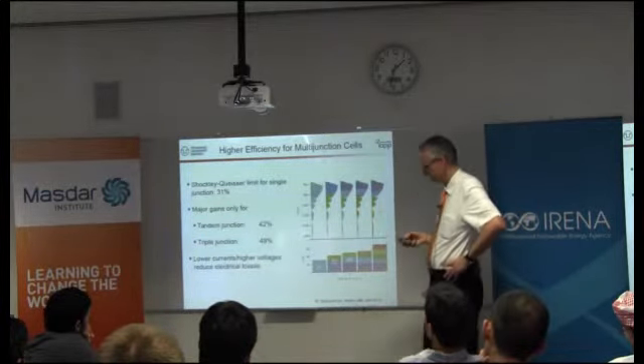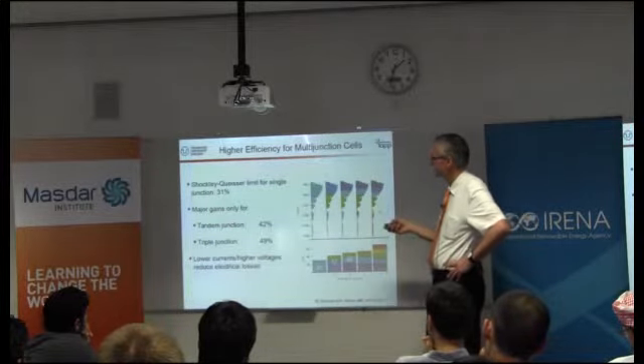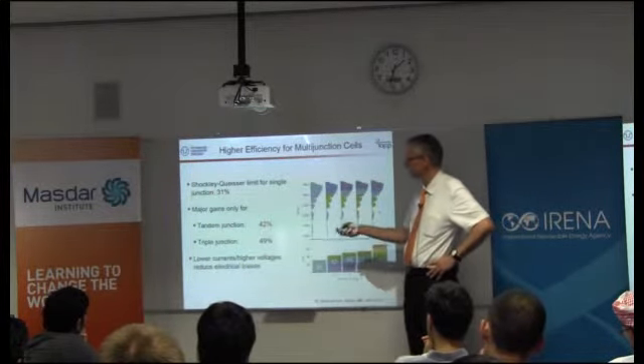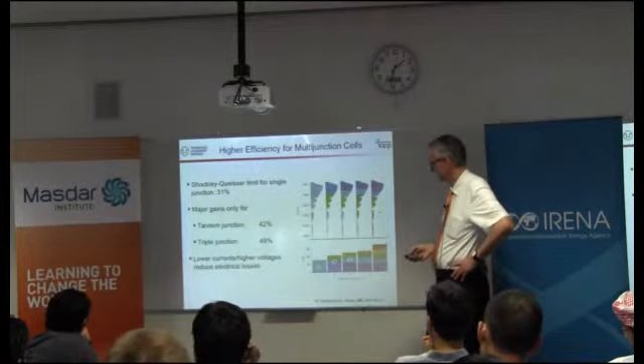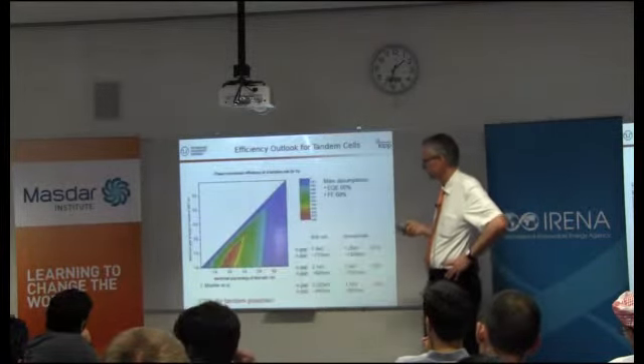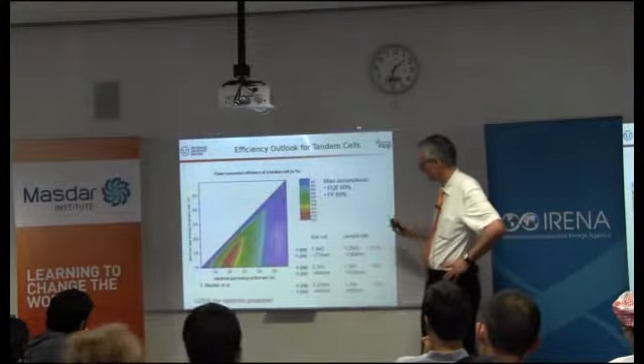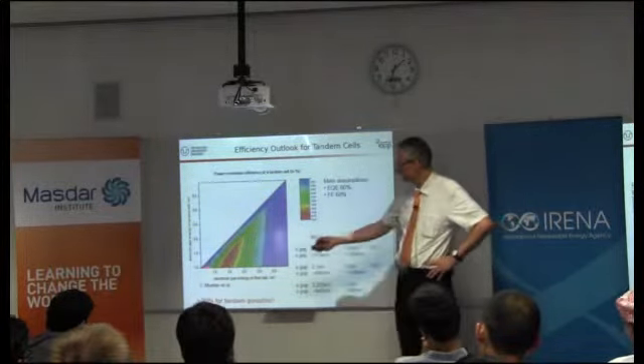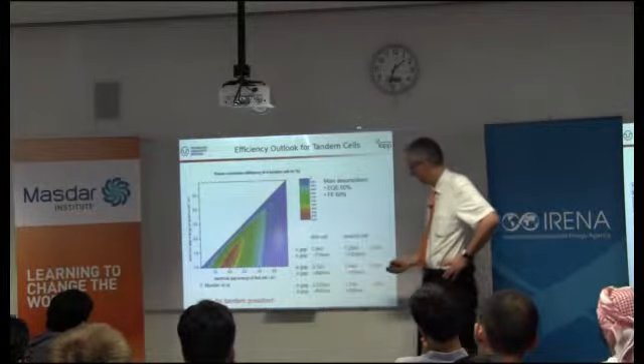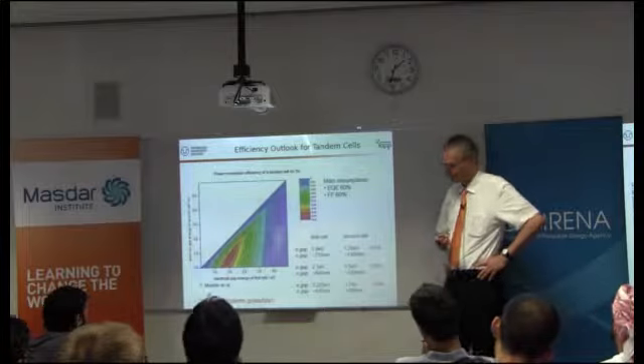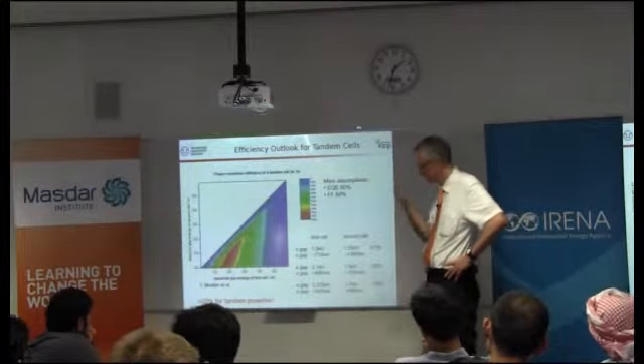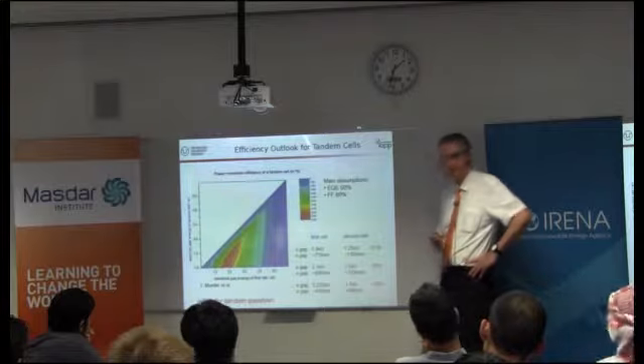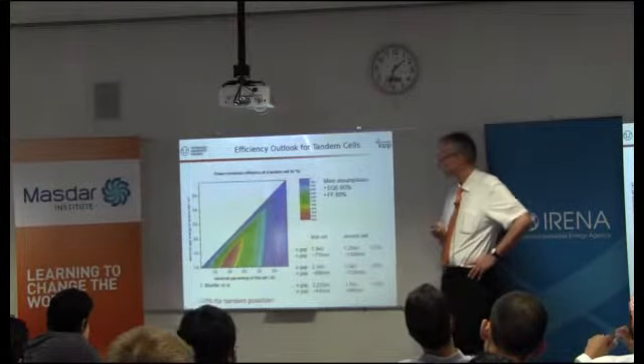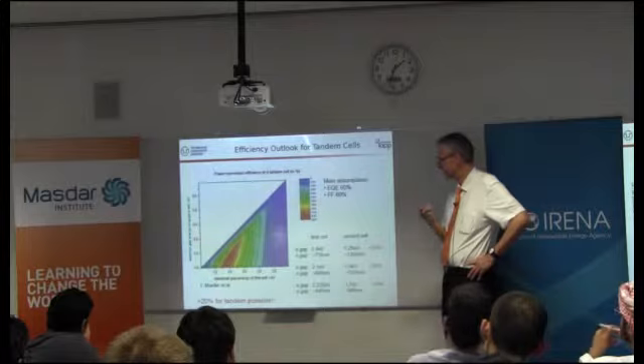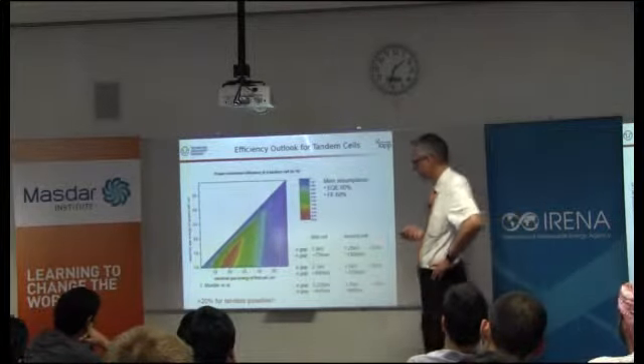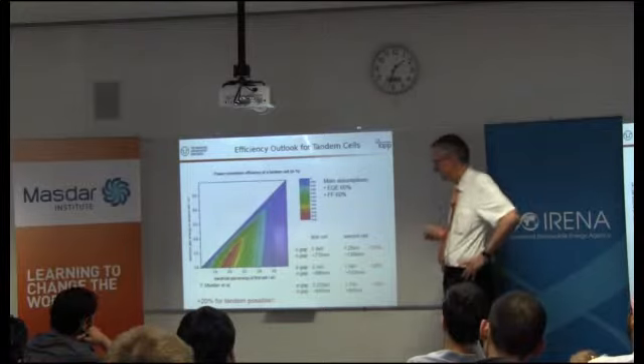But nobody can do an infinite number of junctions. So the way to go is from a single junction to a tandem or triple. And I will show you later that in organics this can be quite easily done. And then if you do again a very reasonable estimate of efficiencies, you end up for optimum gaps at about 21%. And that is my personal motivation. I want to reach these 20–21%, hopefully in a decade or so. And then if the cost is also down, we have a killer product, and maybe we can beat silicon in the long term. We'll see.